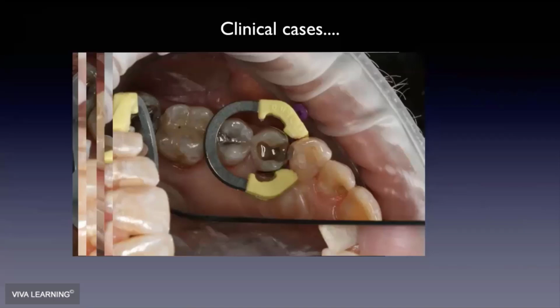If I try to pack body composite to the gingival floor, and especially if there's irregular nuances or 90-degree angles, as I plug a composite into these areas, there's always a chance of my instrument tugging back on the body composite, lifting up, getting voids. And so I'd rather have 0 voids at my base layer or adhesive layer. So I will fill the entire gingival and pulpal aspect of this with a flowable and drag that up partially into the dentin. That way I'm confident that I have perfect adaptation 360 degrees around my restoration.